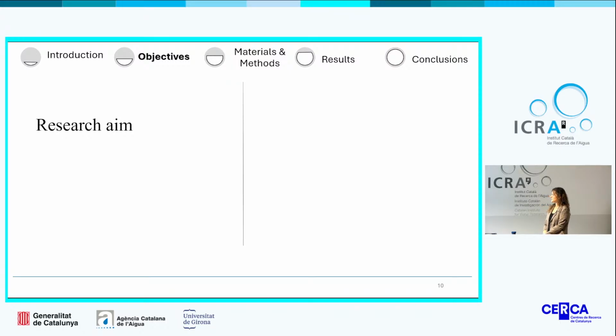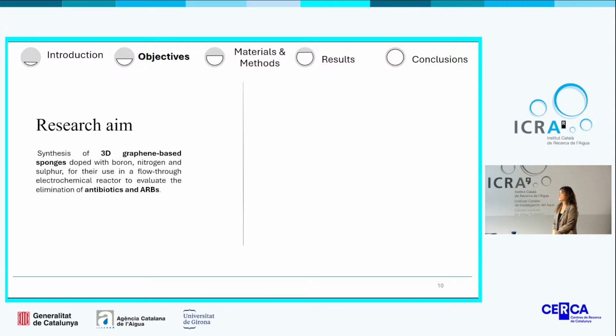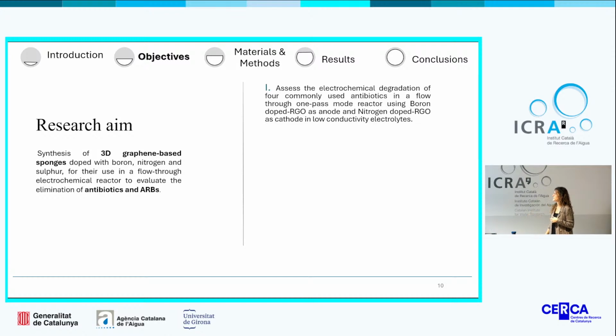Therefore, the research aim of this work is the synthesis of 3D graphene-based sponge doped with boron, nitrogen, and sulfur, and their use in a flow-through reactor to evaluate the elimination of antibiotics and antibiotic-resistant bacteria. In the first chapter of this study, we assessed the electrochemical degradation of 4 commonly used antibiotics using boron as a dopant in the anode and nitrogen in the cathode in low conductivity electrolyte.